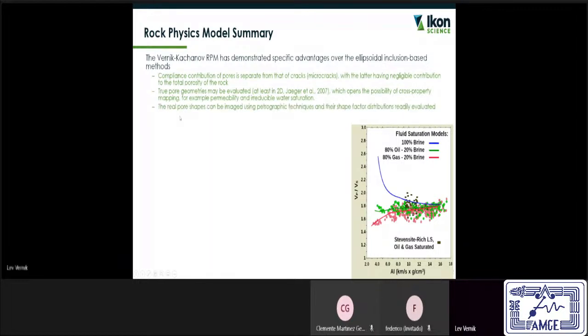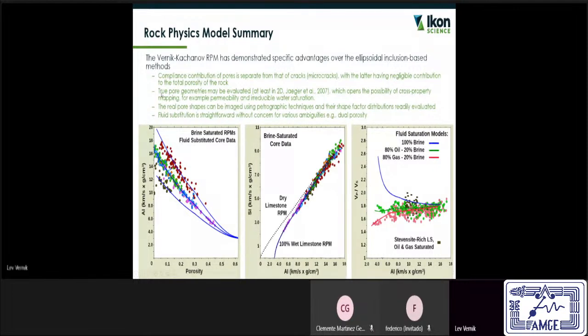So the advantages of the model, we can list them here. The true pore geometries may be evaluated through 2D analysis, and that opens the possibility of cross-property mapping, for example, permeability or irreducible water saturation from elasticity. The significant advantage is that realistic pore shapes can be imaged using petrographic techniques, and the shape factor distributions can be evaluated using image analysis. And then, of course, fluid substitution is straightforward without any concern for ambiguities related to, for example, dual porosity situations like in the inclusion model. An example of that is actually shown here.